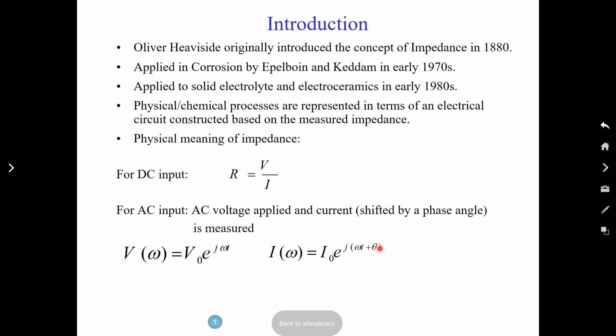For example, let's say you took a stabilized zirconia, an oxygen ion conductor, and you pick up the polycrystalline sample. Oxygen will be moving through the grain at one speed, and when it crosses the grain boundary, it will be different. You can pick that up from the relaxation time, which will be the product of R and C. You will get the values of R and C from the electrical circuit that you use to represent your sample. So that's where we are heading with this.